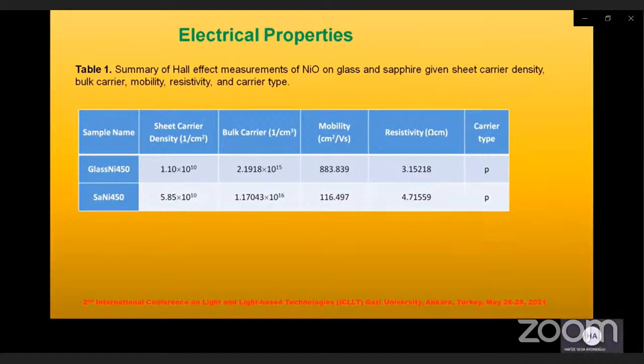While O2 molecules diffused through the nickel film during the annealing process, statistically a number of Ni2+ ions oxidize and form Ni3+ by sharing an electron between oxygen and nickel. In this oxidation process, the vacancy of nickel leads to the formation of holes in oxygen orbitals near nickel sites near the surface, which creates the p-type semiconductor nickel oxide film.